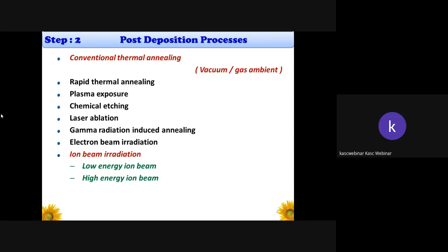This can be carried out in a vacuum atmosphere or in different gas ambients also, to make it suit better for a device application. Then the second thing, the rapid thermal annealing method and even plasma exposure also. Then chemical etching method and laser ablation. These two techniques belong to chemical methods, and then gamma irradiation method and electron beam irradiation method. And at last, I am going to highlight the ion beam irradiation technique to modify the material property as a post-deposition process. Even then, in an ion beam irradiation process, again, it can be broadly classified into low energy ion beam irradiation or implantation and high energy ion beam irradiation. Or we can say that's called swift heavy ion irradiation or SHI irradiation.